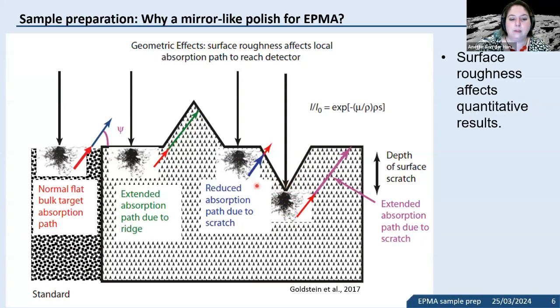there might be less absorption before the X-rays are emitted. All this affects your intensities, and more importantly, the degree to which this effect takes place depends on the X-ray line. So you can't just normalize it to 100. You will overcorrect certain elements and undercorrect other elements if you just normalize it.